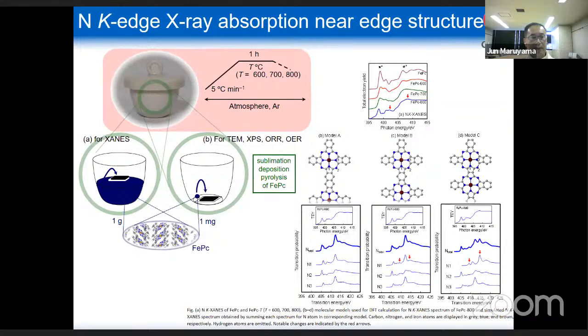And the method is also simple, just introducing the substrate and the raw material iron phthalocyanine in a crucible like this, and heat treated at typically 800 degrees Celsius in argon, an inert atmosphere. And then if we examine the nitrogen physical state by nitrogen K-edge X-ray absorption near edge structure, we can elucidate the two-dimensional lattice-like structure. Actually, this experiment shows that the irons are connected by these nitrogen bridges.